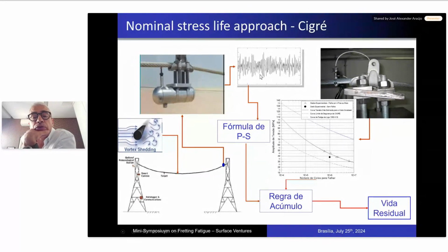Okay, after we apply rainflow, we then go to the laboratory. We develop some S-N curves for this conductor and clamp, which should be the same as you have in the field, and then you can apply accumulation damage rules such as Miner's rule to compute the amount of damage caused in the field. Okay, so we accumulate the damage, and then by using this very traditional fatigue approach, the S-N approach, we can then estimate the residual life.